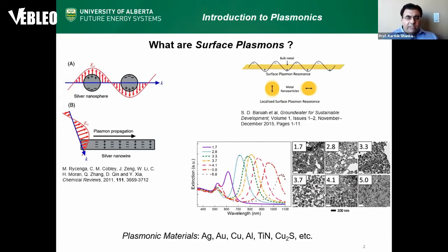So that brings us to one more interesting aspect of plasmonics, which is the exquisite sensitivity of the plasmon resonance to the size, the shape, and the surrounding dielectric environment. So here you see the plasmon resonance of nanorods, I believe these are gold nanorods, being tuned over a very wide range, from green, from about 500 nanometers, all the way to the near infrared. Okay.